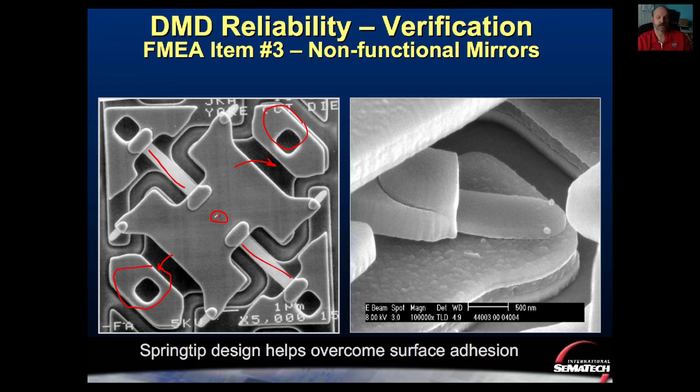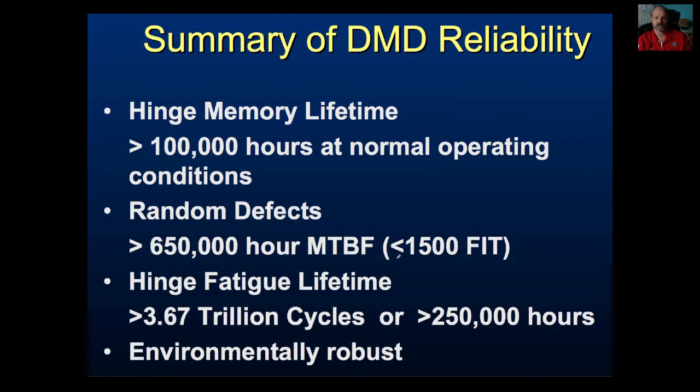it snaps back. Okay, but they had a problem with these things sticking, staying stuck down, so they created these little tabs here, which are little springs, so when it hits, the spring hits and then pushes back up again, and it reduced the stiction. Okay, so that's a problem they had with surface adhesion. So they have hundreds of thousands of normal operating conditions. It lasts for freaking ever.